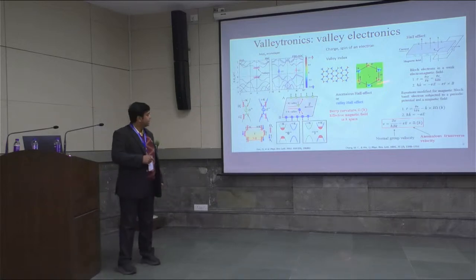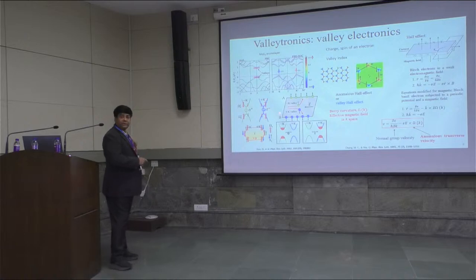How would you do that? That is by using light of appropriate polarization. Like, you need a left circularly polarized light to populate this plus K valley, and a right circularly polarized light to generate carriers in this minus K valley.